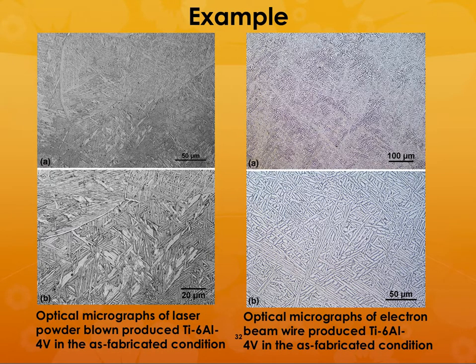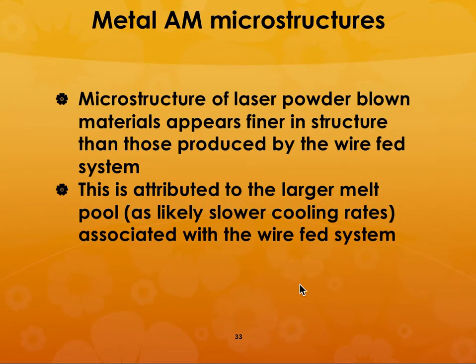So here is the, not scanning electron, it's an optical micrograph of the laser powder blown produced Ti-64 in the as fabricated condition. And if you look at this cross section, you can see that it is different from this, and you get more of an organized structure here than here. So that's the difference, and it can lead to differences in mechanical properties.